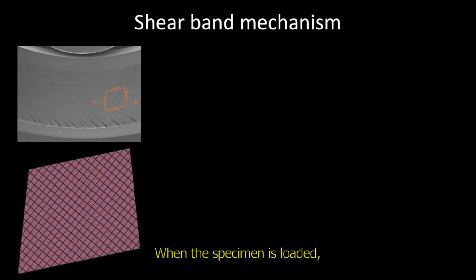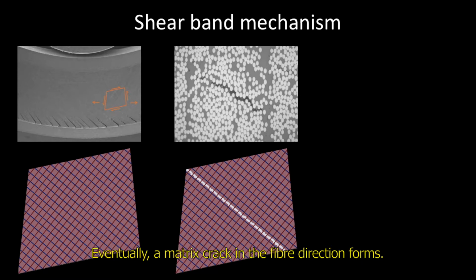When the specimen is loaded, the material is under bending and shearing, with some fibers more in tension than the others. Eventually, a matrix crack in the fiber direction forms. In this case, it forms in the ply with the blue fibers, which is behind the ply with the red fibers. Energy is released, but this doesn't trigger delamination between the plus and minus 45 plies, as we can see